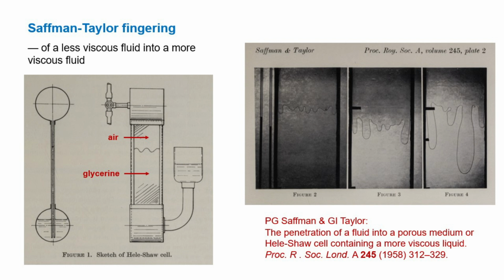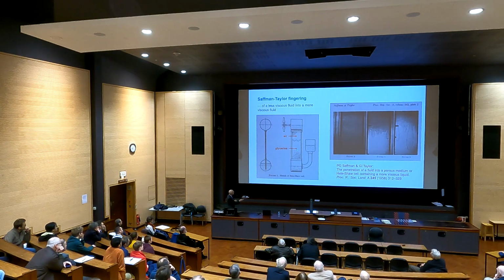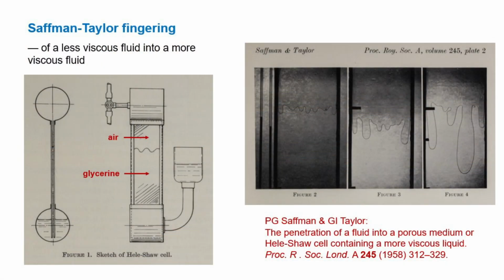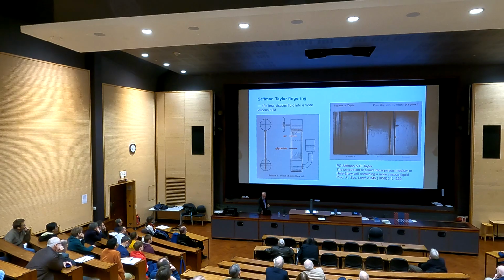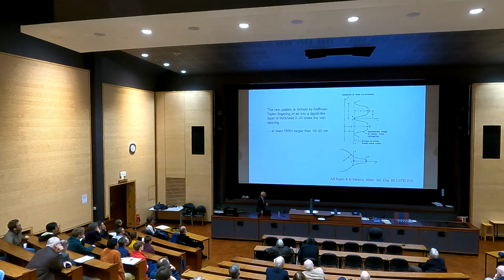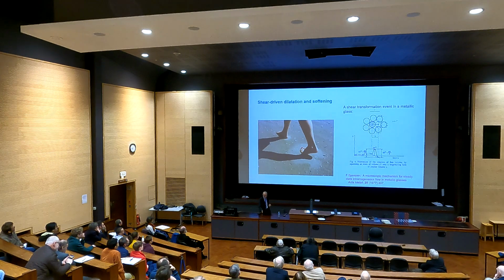In this case, the two media were not two liquids, but a gas, air and glycerine. They're pumping glycerine in from the top. This is a thin plate shape. When you look through, this is the original boundary. And as you push the air in, it doesn't push the glycerine on a flat front, it starts fingering in. And that's exactly what's happening in this liquid-like layer of our metallic glass. And that's been analyzed, and it tells us the liquid layer must be quite thick.